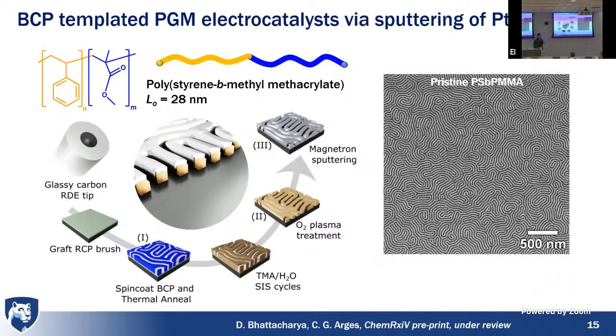Then I'll show you later on. In this methyl methacrylate, we grow an aluminum oxide structure that will serve as our hard mask support. And then we use a reactive ion etcher. These are all tools you find in a nanofab in a clean room, right? We'll etch away the polystyrene block and we'll be left with the aluminum oxide extended surface. And then we go ahead and we sputter the electrode on top.